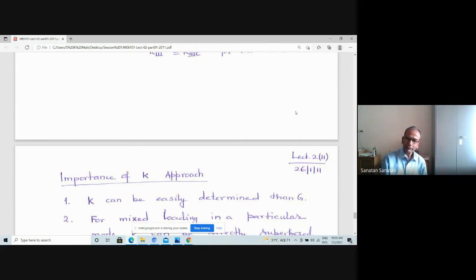Please listen, all of you. When you talk about fracture mechanics, the stress analysis gave rise to the condition that the stress field around the crack tip is an expression involving an infinite number of terms, where the first term is 1 by root r, the second term is r to the power 0, the next term is r to the power plus half, and so on. So the common difference is half. As r tends to 0, all the terms with positive exponent are 0, then the constant term, and then the first term, which is 1 by root r, tends to infinity.